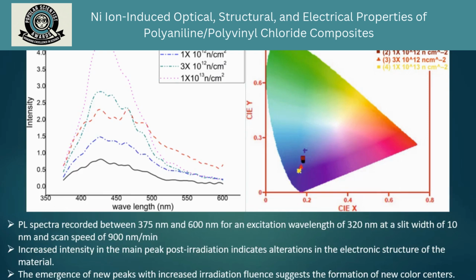First are the results of PL spectroscopy. The PL spectra was recorded between 375 to 600 nanometers for an excitation wavelength of 320 nanometers at a slit width of 10 nanometer and scan speed of 900 nanometer per minute.